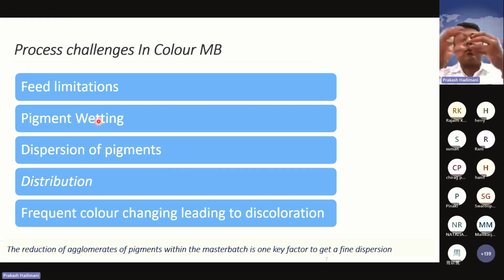If you are not using a proper wetting agent on the pigment, there may be chances of wear and tear on the extruder and the shear rate will increase. Then again, you are going to break the pigment particles. That we call degradation: if you apply so much shear, it's a degradation. And dispersion of the pigment plays a vital role. It all depends on your screw design and the formulation, distribution also, your selection of the kneading block, and frequent color changes leading to discoloration. One hour before you are running red color, after that you are going to change the color. Small traces of color lead to discoloration of your final compound.